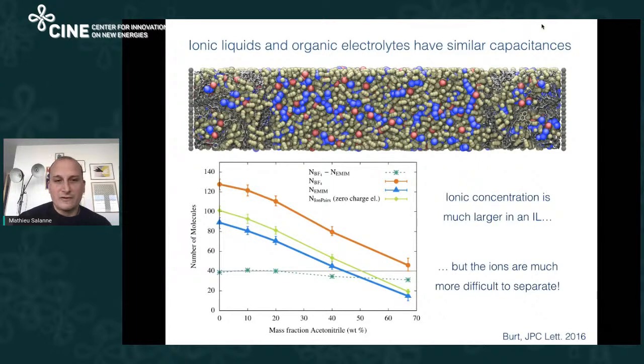It's how much you can separate cations from anions. And so, in fact, when you apply a voltage, here we are looking at the positive electrode, you see that the number of anions goes from the green line to the orange line, so you have an increase. And the number of cations goes from the green line to the blue line, so you have a decrease. But the extent of the difference between anions and cations it's always the same.